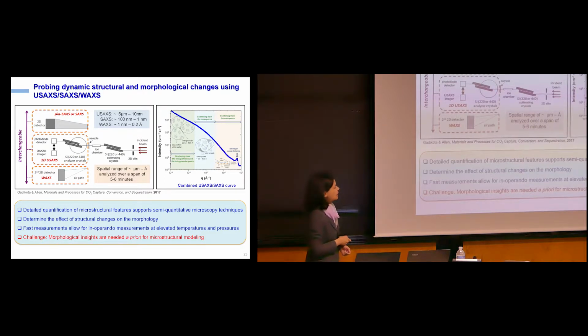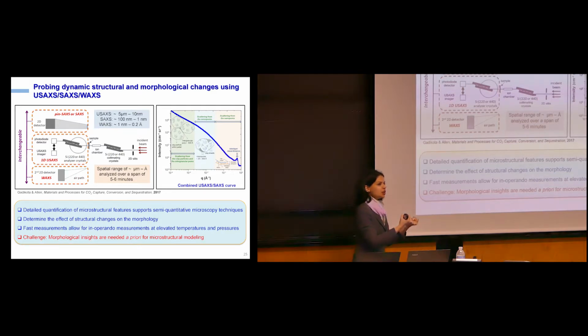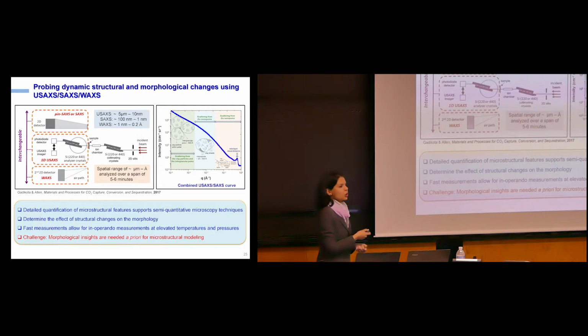The challenge is that you could scatter from a slice of cheese, you could scatter from a slice of wood, and your scattering curve could actually look the same. So you need to have some a priori insight into what the morphology of this material actually looks like, even before you can go in and start extracting some of these microstructural features of these materials. So we started doing some X-ray scattering on these effectively disordered materials, if you like. Basically, they're a bunch of polymers organizing themselves around silicon nanoparticles in the presence of CO2.